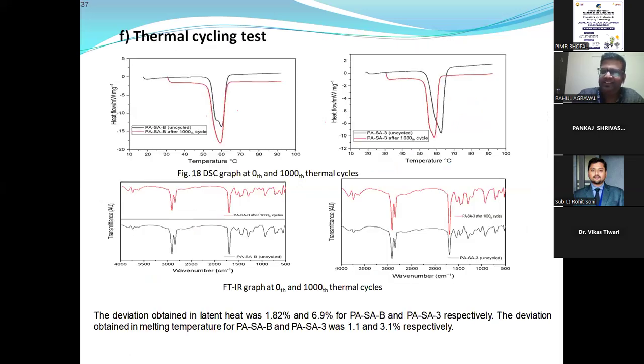This thermal cycling test also, that's a thermal cycle tester, in which continuously we are solidifying, we are melting the PCM, then solidifying, melting the PCM, solidifying. So in a day, 25 tests we can perform. So approximately after the 1000 cycle, as 0 cycle and 1000 cycle, we have seen that we do not get so much difference. That our PCM is also stable after 1000 cycles. So this is a thermal cycling test we are using for the energy storage materials, basically.